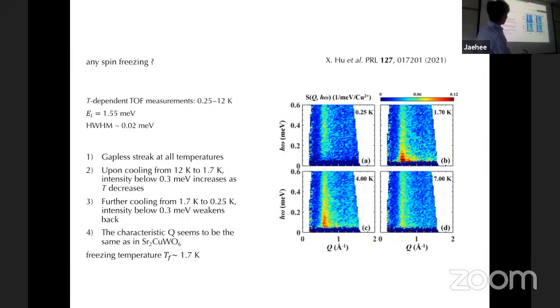temperature. So you can see here at 7 Kelvin is a nice streak. Yeah, it's like a magnon. Then cool down to 1.7, and you can see the very low energy spectral weight increases, becoming brighter and brighter, because the spectral weight shifts to low energy. That's, if you remember, like the case of SCGO. But then again, below 1.7 all the way down to 0.25 Kelvin, this low energy spectral weight gets depleted. Like SCGO, yeah, it's a deja vu of SCGO.